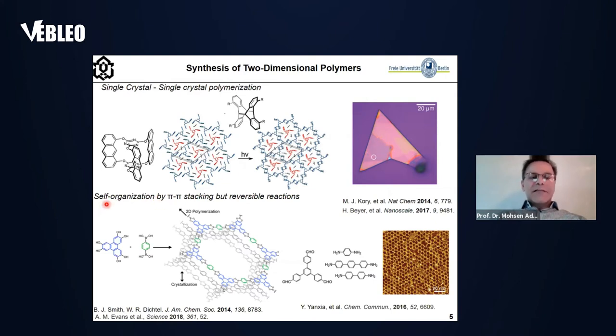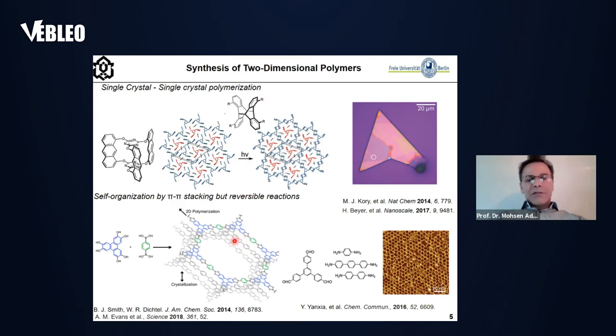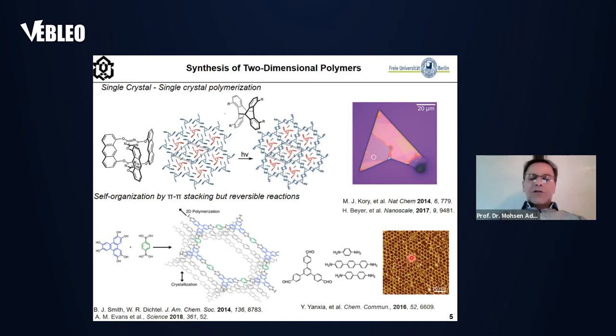The last method is self-organization by pi-pi stacking. The most well-known materials produced by this method are boronate ester two-dimensional covalent organic frameworks. In this case, the pi-conjugated backbone of each layer forces the next sublayer to grow in two dimensions. Two-dimensional polyimines produced by Schiff-base reactions are another type of two-dimensional polymer produced by this method.